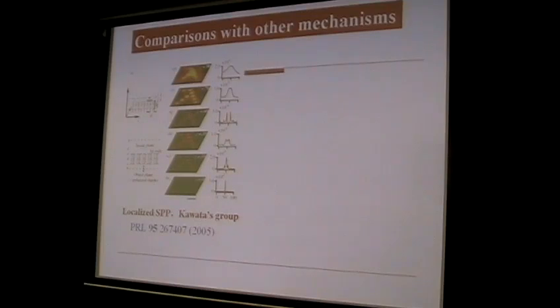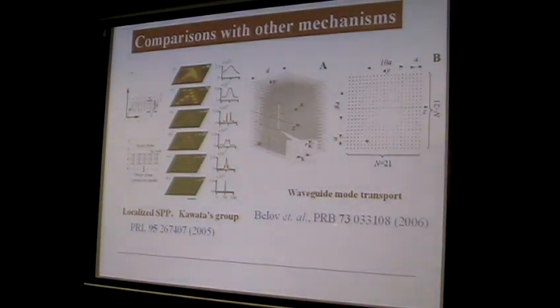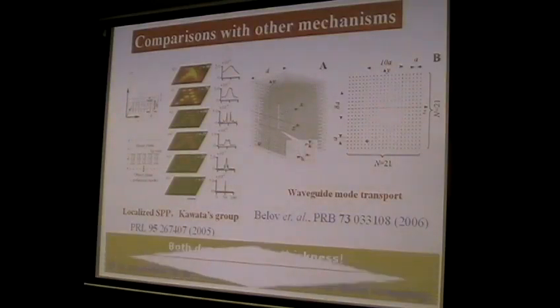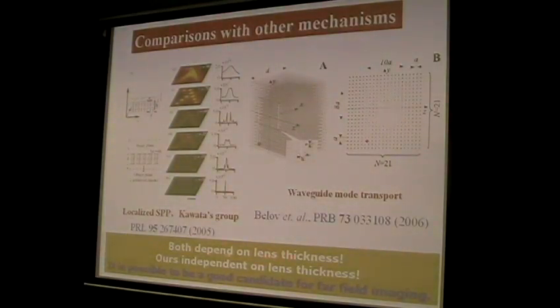We compared with other lensing mechanisms and found that we do have some unique properties. In 2005, Kawata's group in Japan proposed using the localized surface plasmon of a metallic rod to make a metallic lens to focus images. Another group in England proposed using waveguide mode transport in wire media to perform the imaging. Compared with these, both structures depend on the lens thickness, and our lens is independent of the lens thickness. So it's possible to be a good candidate for far-field imaging if you can make the device thicker and transport the image over a long distance.